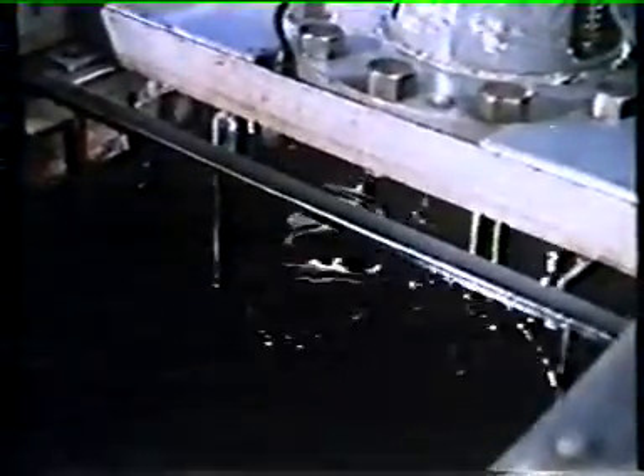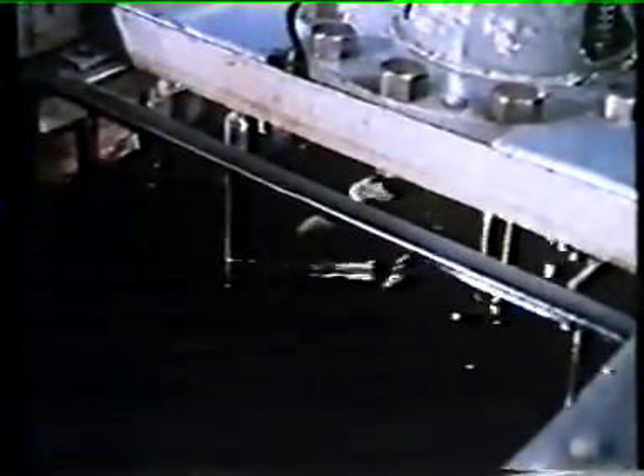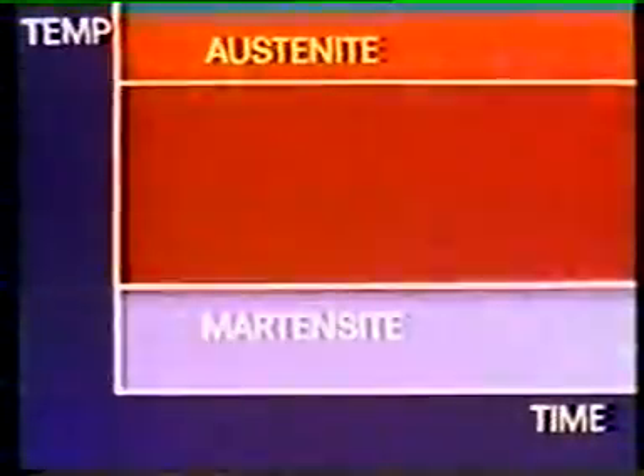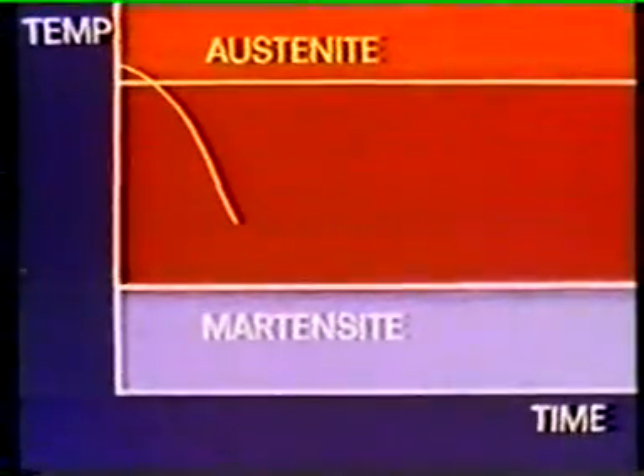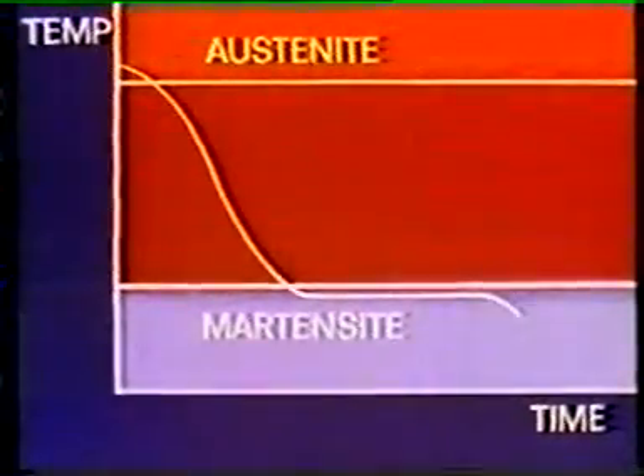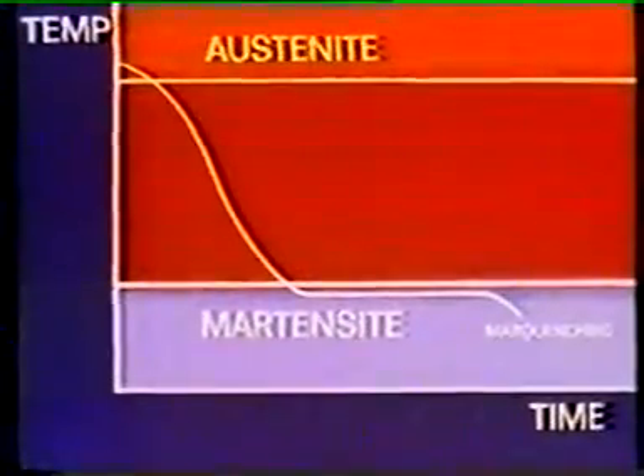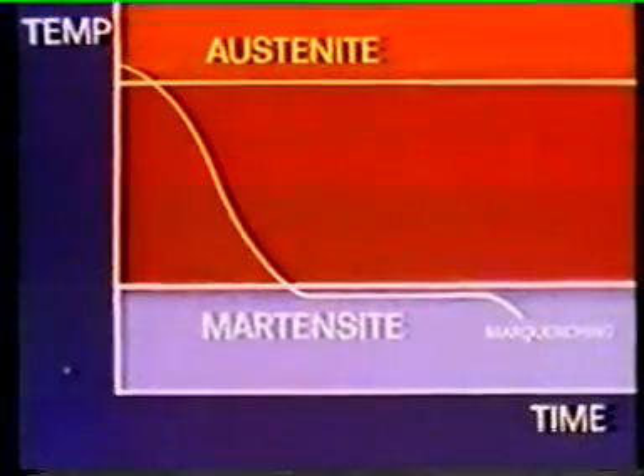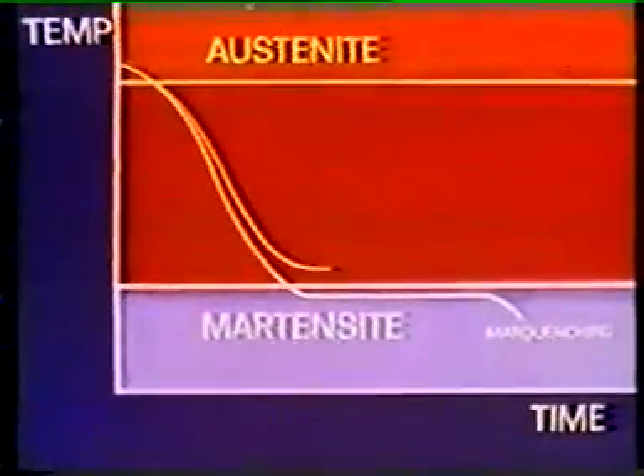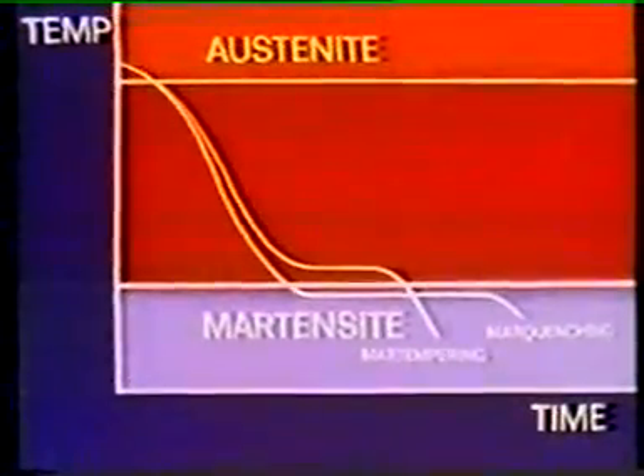It so happens that the production of case-hardened drill chuck sleeves illustrates one more variation on the process of heat treatment. The oil quench tank is lined with vertical bars. They're electric heating elements. They keep the oil at a temperature of 140 degrees centigrade. So the components are quenched not in cold oil, but in relatively hot oil. Here's the effect in graph form. Cooling ceases after hardening has begun, and the temperature is stabilized at this point to minimize distortion. This method is called Marquenching. The rate of cooling may be controlled at different temperatures to minimize distortion, or to produce special properties in the hardened metal.